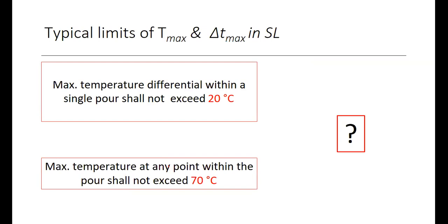Suppose we are producing a cake or some sort of dodol or whatever. If I make a cake and put it on top of a desk, and check after a certain period of time, the temperature of the surface will be lower than the temperature at the core, or the middle, because the middle doesn't have much opportunity to dispose of the heat generated. It gets accumulated and the temperature rises. So temperature difference means the difference between the highest temperature position of the concrete and the lowest, usually the middle and the surface.